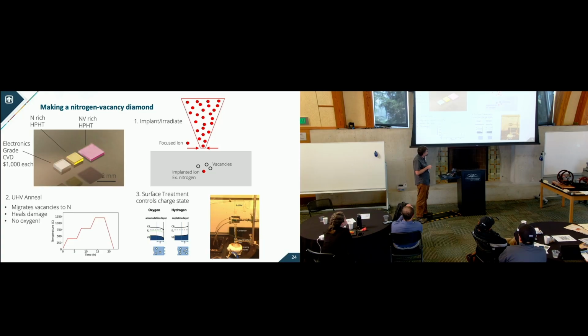So we typically oxygen terminate. Oxygen has a high electronegativity, so it pushes electrons back into the nitrogen vacancy, making it an NV minus. And we clean it with this triacid clean, which is perchloric, nitric, and sulfuric acid that's boiling. That cleans the surface as well as possible. Thankfully, I don't do that. The students and postdocs do that, and it's probably best anyway.